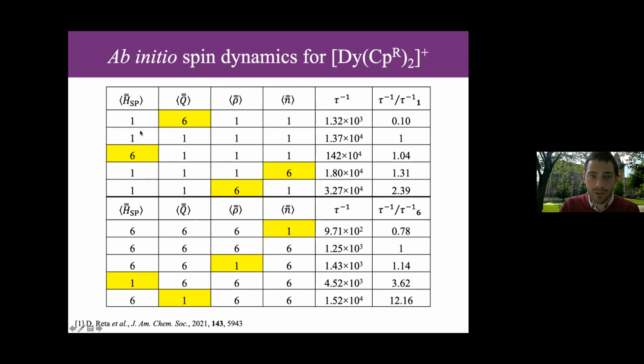Now, if we swap out the occupational factor, so that is the temperature dependence of the modes, for that of Layfield's dysprosocenium molecular magnet, so that is the slowest, compound 6, then we can reduce the relaxation rates by a factor of 10. Whereas if we do all of the other single swap outs, so that is we change the spin phonon coupling, we get a barely noticeable change. If we change the average number of modes, again, it's not an order of magnitude like this one is. And then finally here, we could change this density of states part. And again, it's a bit of a change. It makes it twice as fast, but it's not an order of magnitude. This is a factor of 10, right?